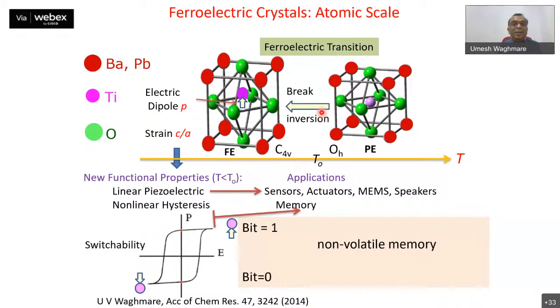So at atomic scale, a typical ferroelectric looks like this: we have a cubic structure of, for example, barium titanate, where the titanium atom is at the center of this octahedron of oxygen. This is the beautiful cubic perovskite structure. And as you lower the temperature, you get a low symmetry phase where the titanium atom gets off-centered spontaneously, giving a dipole moment because titanium is positively charged and oxygens are negatively charged.